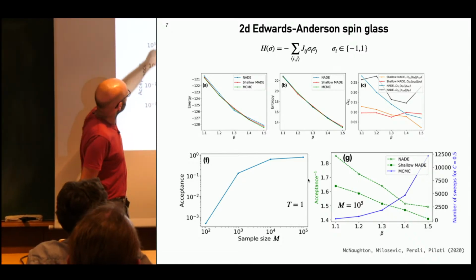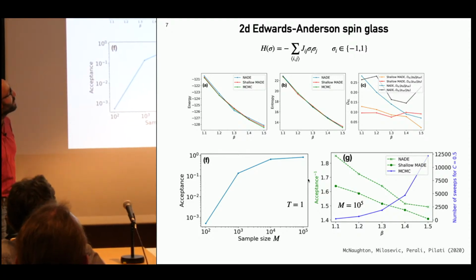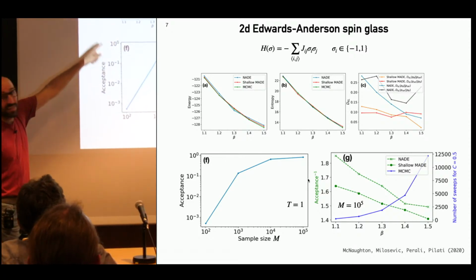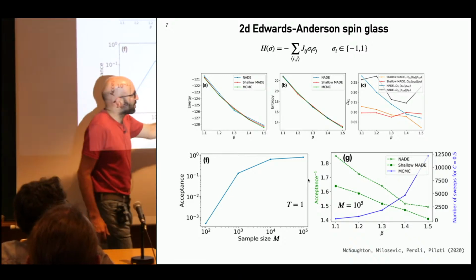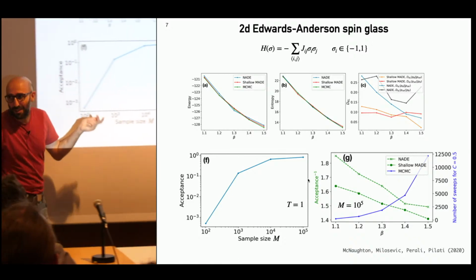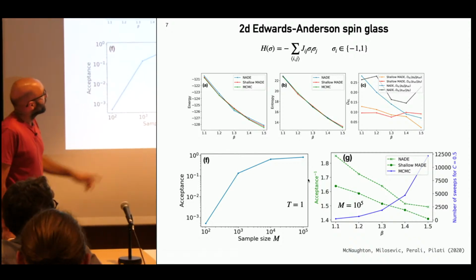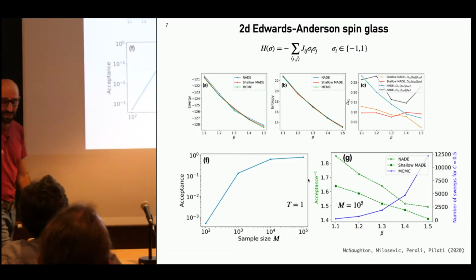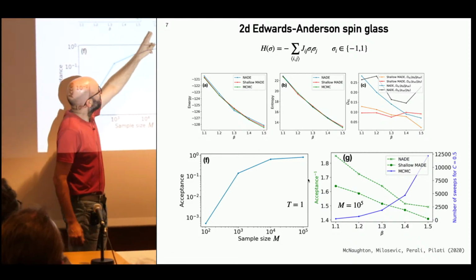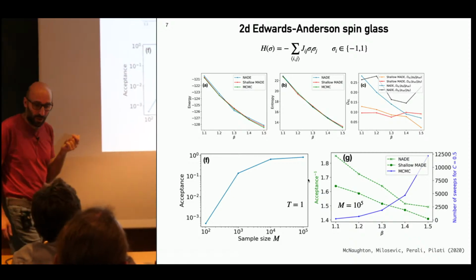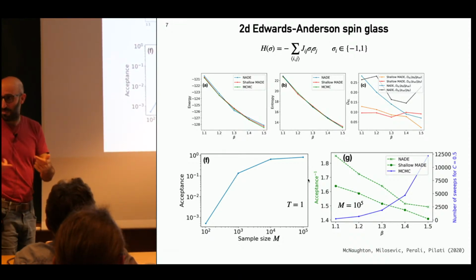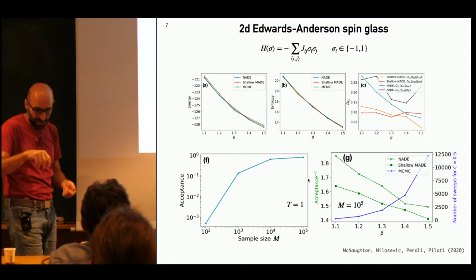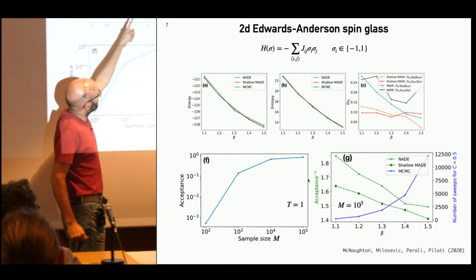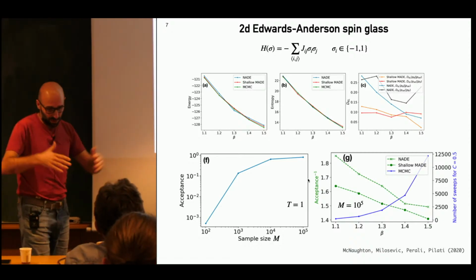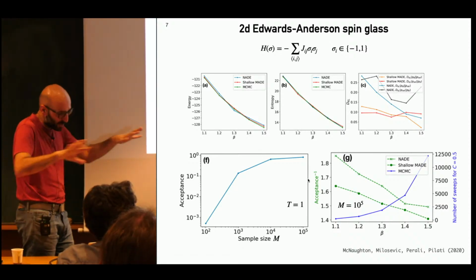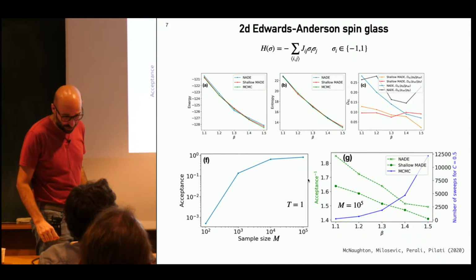So what you see here is, for example, the energy of the model that we learn compared to the energy that we get from local Monte Carlo. Here, the local Monte Carlo is still doable down to 1.5, so we can compute the energy and compare, and it's very good. We can also compute the entropy by integrating the specific heat when we go down in temperature, and compare it with the entropy of the model that we learn. That is easy to compute because you can sample and then just average the log of the probability on the sample that you generate. And you see that the entropy also is very close, which means that there is no mode collapse. The two models have the same entropy, so they are spread over the same space of configurations.